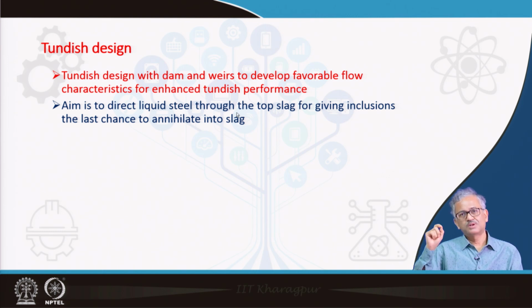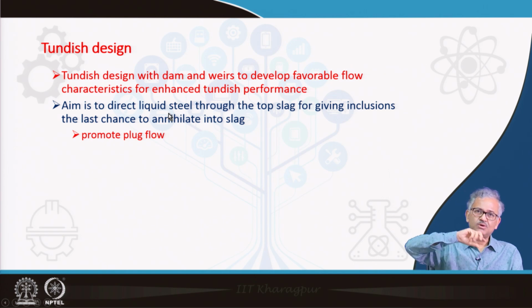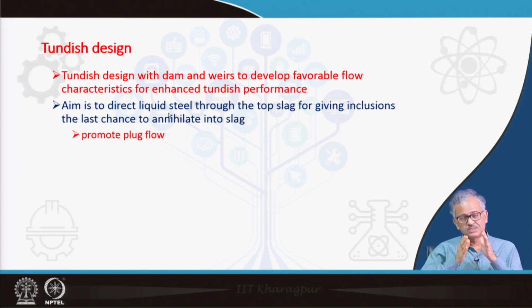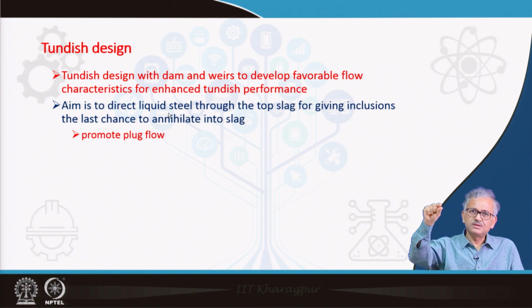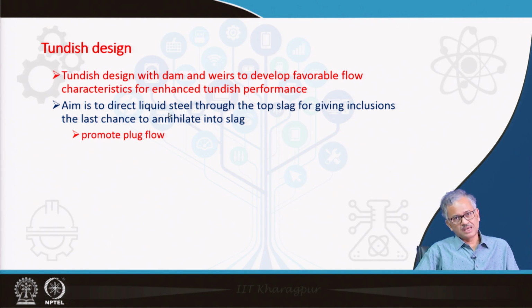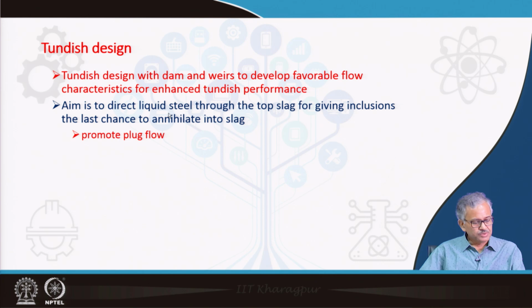Plug flow is one of the real flows. There is an idealistic flow, which is called the plug flow. I will come to that later on. Anyway, the aim is that, that is the tundish design. So, as I said, it is to promote plug flow. Plug flow can give this type of flow, such that all the fluid elements move at a particular velocity, and they have a constant residence time, and they follow a particular path. So you can make a plug flow in such a way that the liquid steel moves through the top and then comes to the exit. So during their movement in contact with the slag, basically the inclusions will get removed. I will come to that.